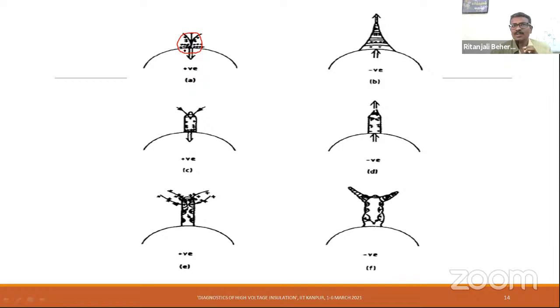So the C-H bond will be broken, and as time goes, this continuous process will lead to many more bonds breaking, and a micro void will form. Once the micro void forms, that gives rise to discharges, and something similar to what I explained in the previous 2-3 slides will take place. So that will lead to more and more branches. The micro void that started here gives rise to a small tubule, and partial discharge would take place in the small tubule, giving rise to further channels.